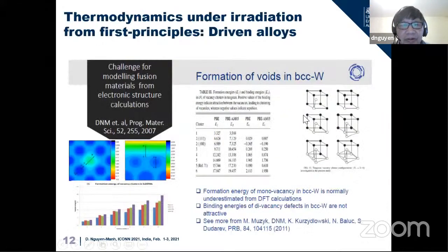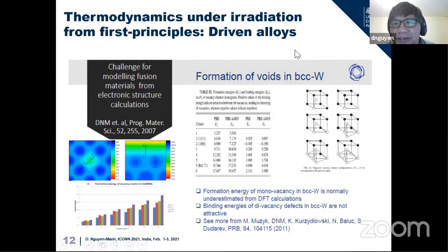Coming from ab initio calculation, it comes back to what Professor Cavazzoli mentioned, that the exchange-correlation function is really important. For tungsten, it is a very important problem in predicting the defect properties. For example, predicting the vacancy in tungsten is not easy, because the formation energy predicted from DFT calculation with the exchange-correlation function is about 3.3 for the point defect vacancy, whereas the experimental data is about 3.5, or 2 until 4 electron volt. The missing thing is that the treatment of the vacancy and its neighborhood is not properly correct using the exchange-correlation within the PBE functional, for example.